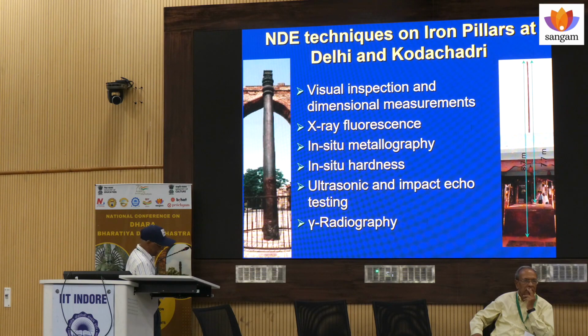Okay, this is the Delhi Iron Pillar. So we used a number of investigations. These include visual inspection, dimensional measurement, X-ray fluorescence, in situ metallography, in situ hardness, ultrasonic and impact non-destructive testing, and gamma radiography. Particularly the gamma radiography has been done in the night because of the hazards involved, and also to see that the visitors are not affected by these investigations.